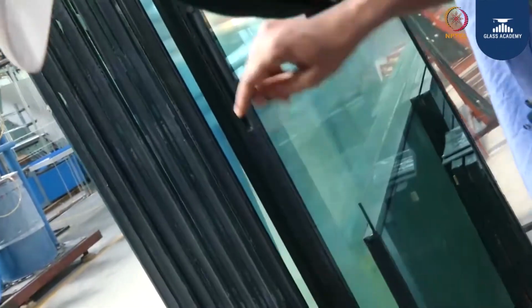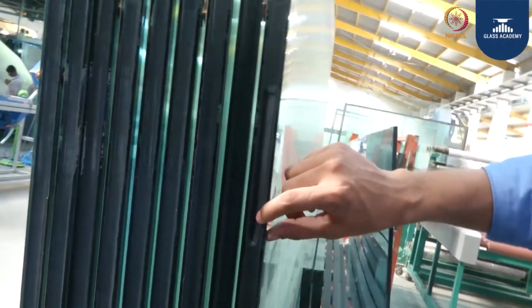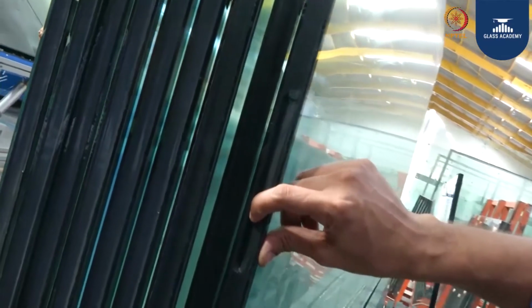Now if you see here, it is not completely removed. Part of the silicone is still sticking to the glass as well as the spacer. So this is known as the silicone peel adhesion test.